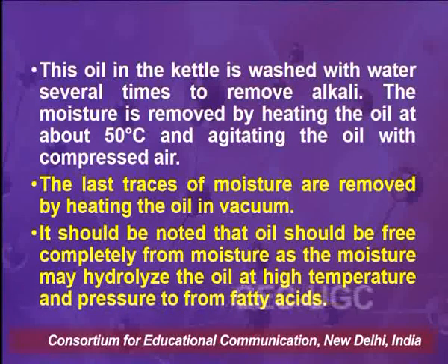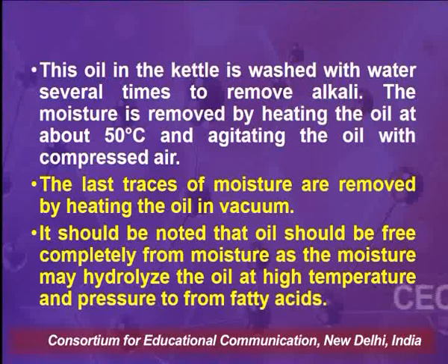The moisture is removed by heating the oil at about 50 degrees centigrade and agitating the oil with compressed air. The last traces of moisture are removed by heating the oil in vacuum. It should be noted that the oil should be completely free from moisture, as the moisture may hydrolyze the oil at high temperature and pressure to form fatty acids.